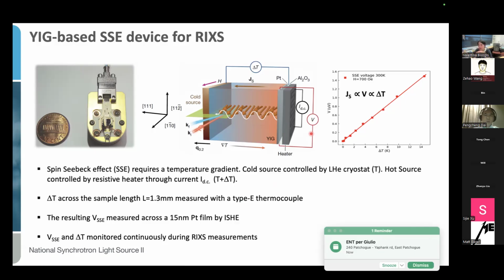I see, but then wouldn't you expect that if you only see the spin Seebeck coefficient changing, you would expect it to be greatest as you gradually decrease the energy even more, right? 10 meV, 9, so it should in principle be most efficient near the quasi-elastic line, right? I mean, except for the gap. So if we would repeat this measurement at smaller Q. Yeah. So smaller acoustic magnon energy, then the change should be stronger. Yes. Did you see that?